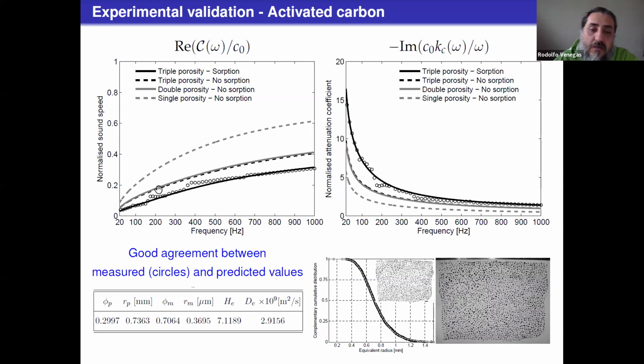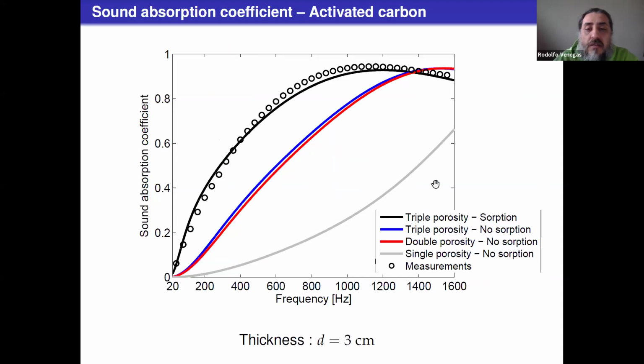In circles, these are measurements, and in black lines are the predictions of our model. In terms of sound absorption, let's imagine that we have a granular material with solid grains. This is what we would get as sound absorption. And then if we consider triple porosity material with sorption, we get this black line. So it's a significant jump in the sound absorption coefficient from, let's say, smaller than 0.1 up to about 0.45 at 200 Hertz. And again, the circles are measurements, and in black we have the predictions of our model.